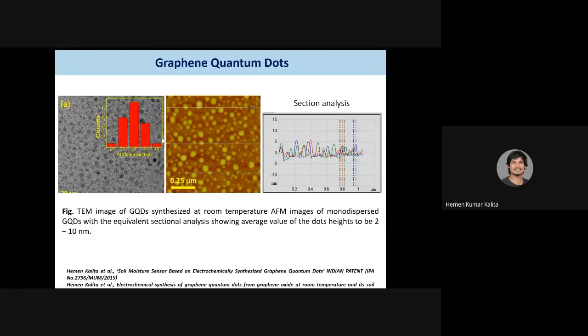As I told you, graphene thickness is very important to confirm whether it's a graphene or not. So we have done an atomic force microscopy analysis, and this is the atomic force microscopy image, and you can see that the thickness of the graphene quantum dot comes around 2 to 10 nanometer, which is exactly fitting with the literature. So we confirm that these are graphene quantum dots.